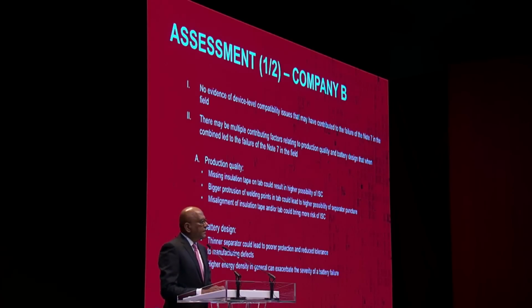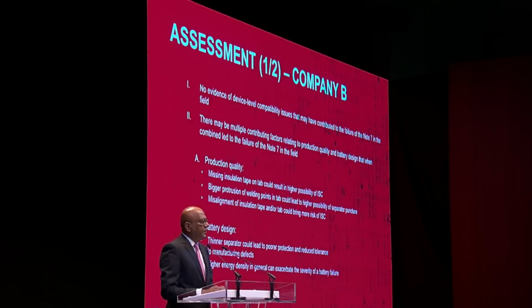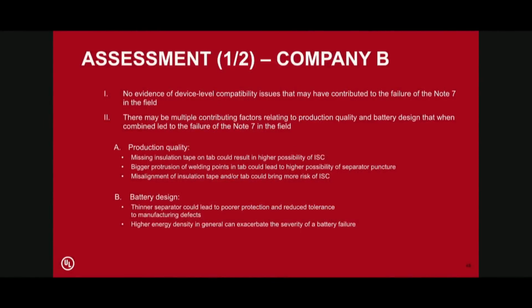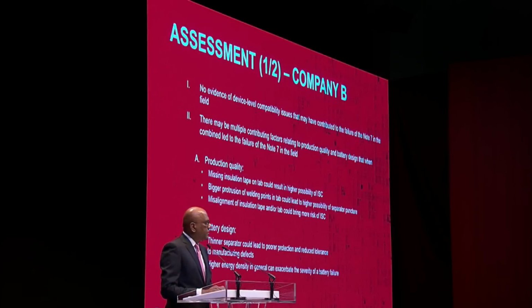There may be multiple contributing factors related to production quality and battery design that in combination led to the failure of the Note 7 in the field. The production quality issues were missing insulation tape on the tab, which could result in a higher possibility of internal short circuit, bigger protrusion of welding joints in the tab, which could lead to a higher possibility of separator puncture and thereby an internal short circuit, and misalignment of insulation tape and/or tab, which could also increase the risk of an internal short circuit. Contributing factors from battery design were thinner separator, which could lead to a poorer protection and reduced tolerance to manufacturing defects, and higher energy density of the batteries in general, which can increase the severity of a battery failure.